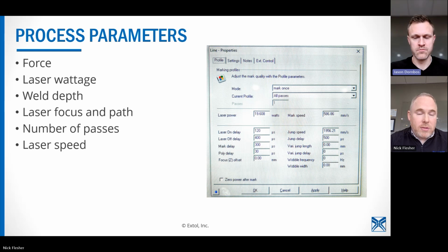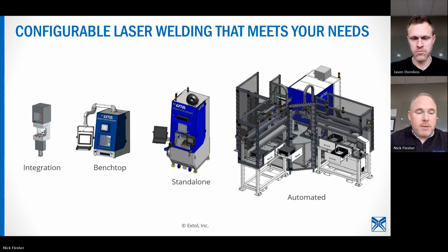This is kind of an interface to do power and speed. Most of this webinar is around quasi-simultaneous, and those can be anywhere from, contour welding is sort of the slower versions of that, 50 millimeters per second all the way up to 3,000.